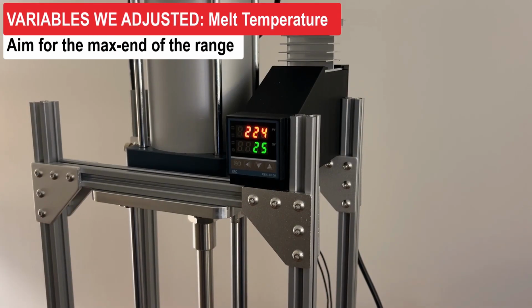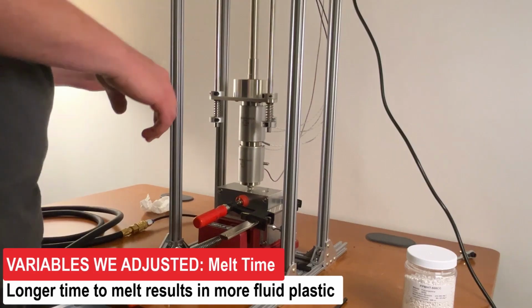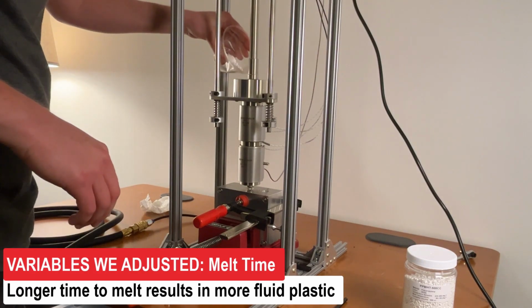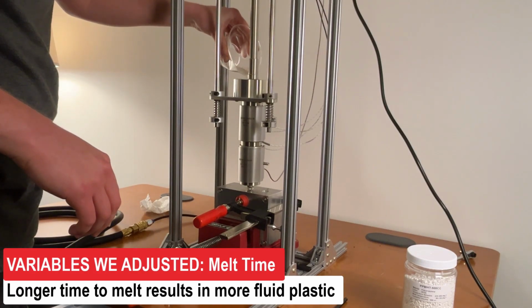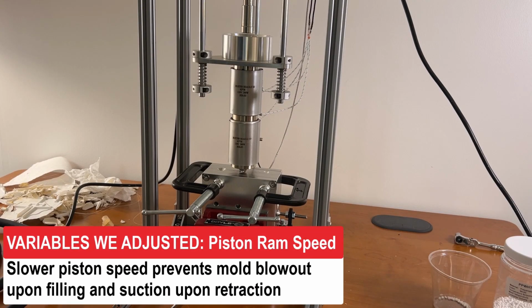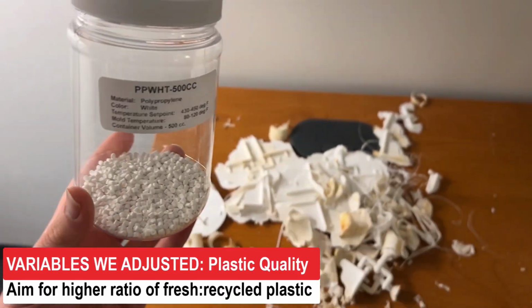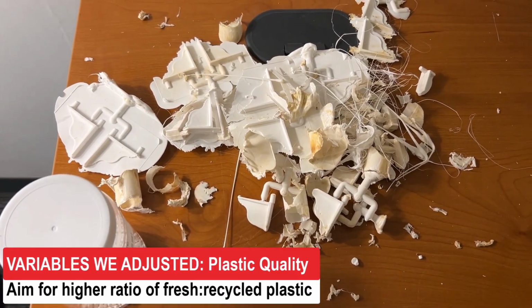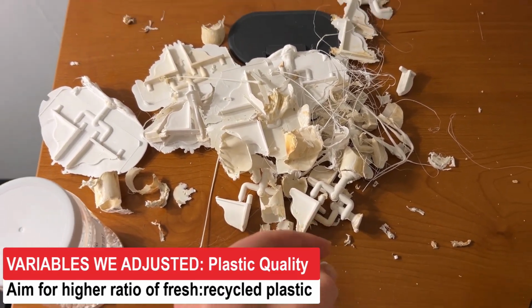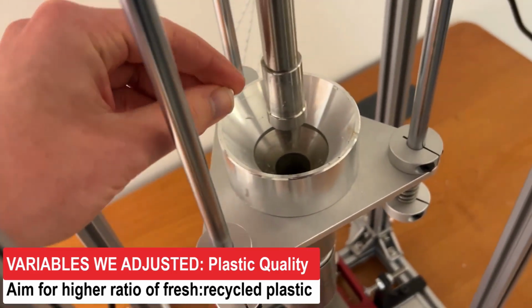We played with the temperature, varying it between 220 Celsius all the way up to 245 Celsius, where we found good results at higher temperatures. Waiting different durations after refilling the chamber with pellets, the longer the better. Reducing the speed of the ram going down and up. Slower was better because too fast resulted in overfilled molds and suction. Varying the ratio of recycled plastic to fresh pellets inside the chamber. We don't have a grinder, so recycled plastic melted much slower, plus more fresh pellets performed smoother fills.